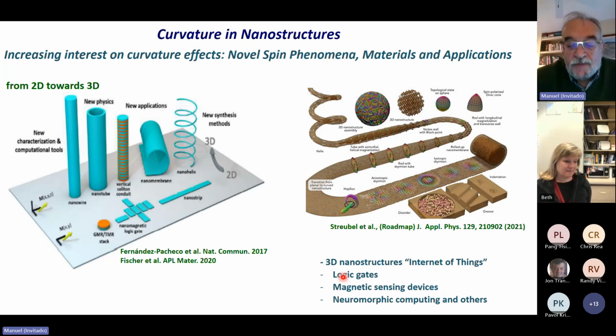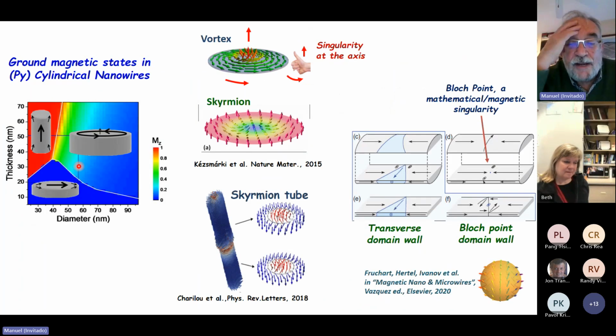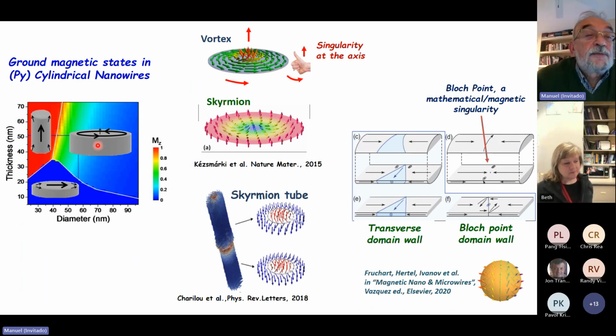Well, let me go now to the nanowires. As you may know, there is an increasing interest in the effects of curvature on magnetic nanostructures. Up to now, practically all nanotechnology materials are based on two dimensions: thin films, multilayers, etc. But what happens when we have a third dimension? That can be achieved, for example, with a flexible film like this one here, a nanomembrane, or in the case of nanotubes, nanohelices, or in the case of nanowires, which is our field of expertise. In the case of nanowires, because of the cylindrical geometry, and considering only the shape anisotropy, as for example in permalloy, we have three ground magnetic states: the axial one, the transverse one, and the vortex one.